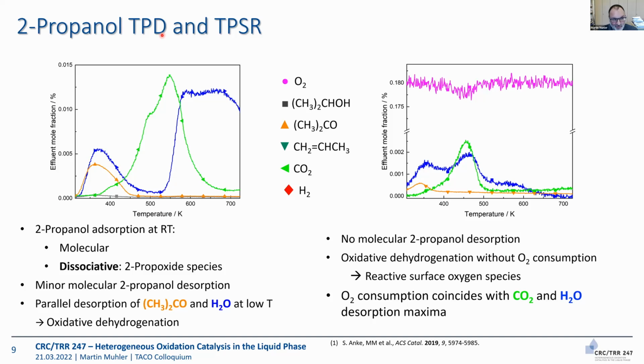We can adsorb 2-propanol and desorb it like in ultra-high vacuum. The only difference being it's now a much slower experiment, and we need a carrier gas, helium, to transport the desorbing molecules from the small fixed bed into the mass bag. And when we adsorb 2-propanol and start the heating ramp, then you see immediately, oh, fine, we get acetone and water, telling us it's the oxygen from the catalyst that is ending up in water.